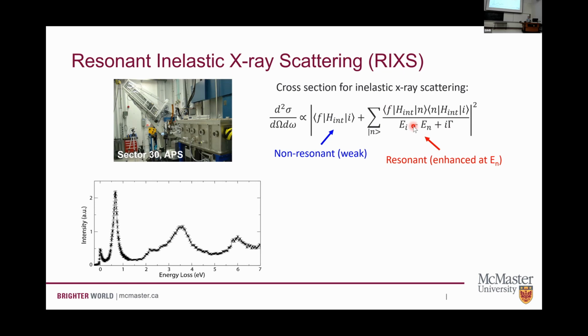It also makes the measurement element and orbital specific, so you can get some really detailed information here. So if we tune to an iridium absorption edge, all that we see is a signal that's coming from iridium. So this is a RIXS spectra. Its intensity is measured as a function of energy transfer at a particular momentum transfer or position in reciprocal space.